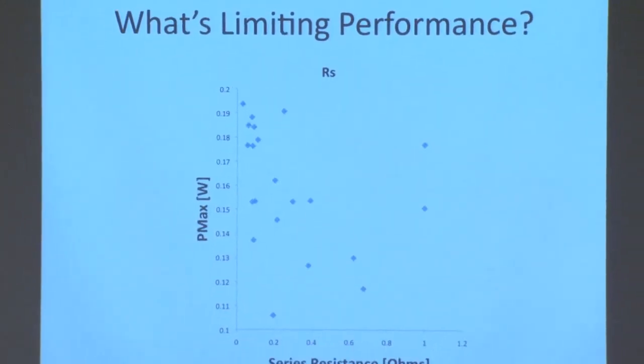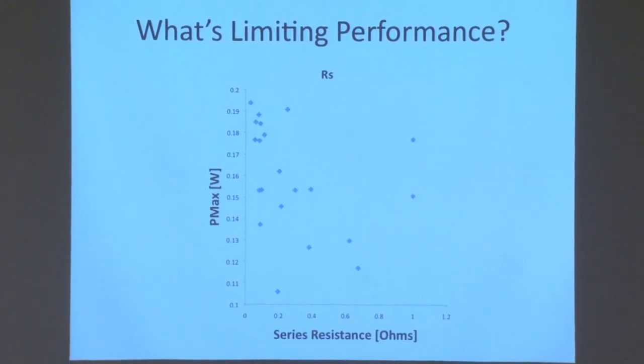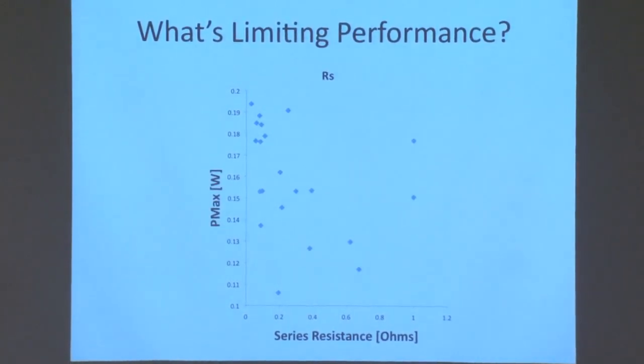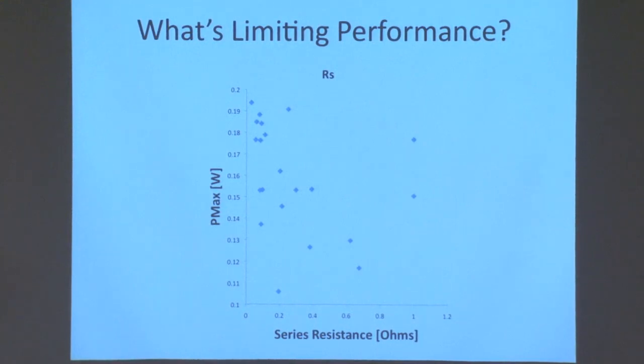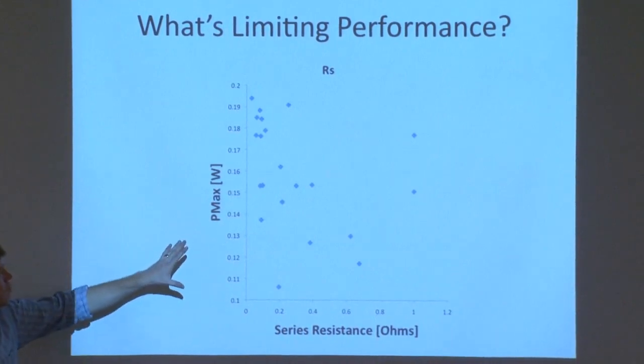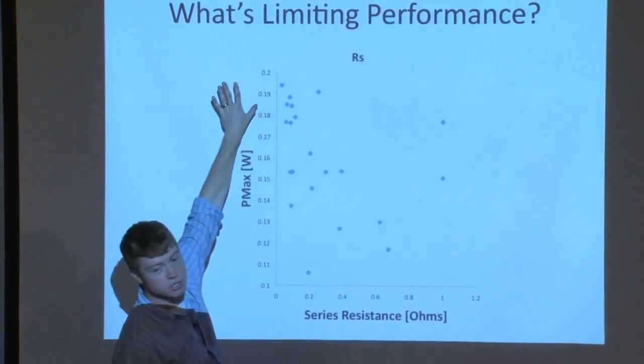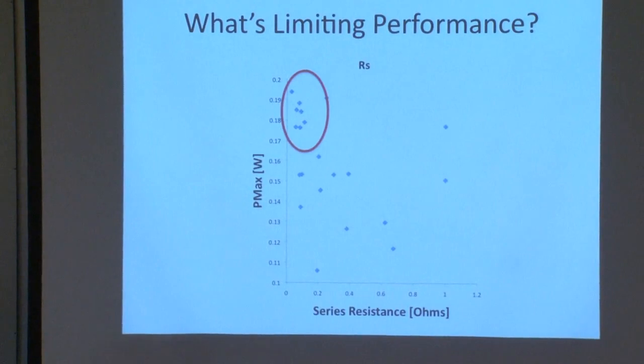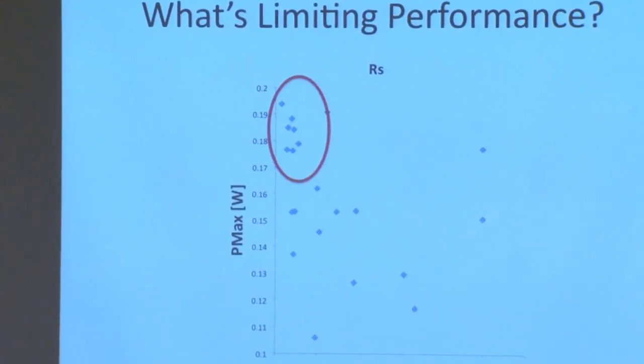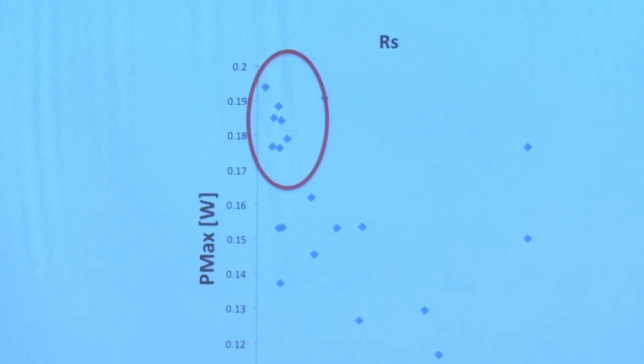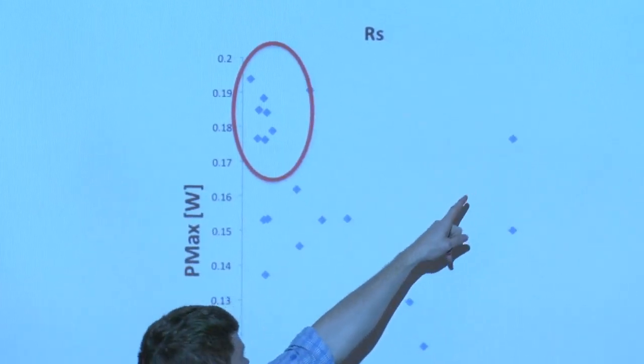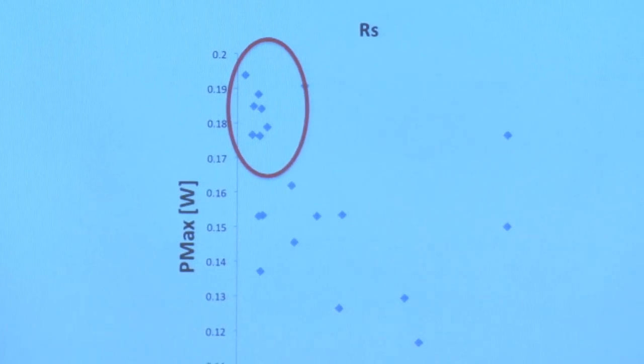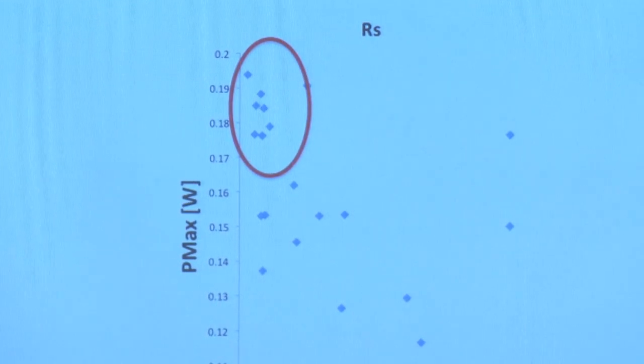Additionally, I plotted the series resistance that I calculated from your dark IV curves against your maximum power. I also removed all the cells that were broken. I'm sure if I actually normalized them, some of the cells that were broken actually performed a lot better. And I'll get into maybe why that was the case in a second. But really the take-home message is that our best performing cells are all clumped over here. And so you can see that our best cells have a very low series resistance. That's not always the case. There's some outliers like this guy here, and I don't know how that happened. But some really interesting things going on. I'm still trying to sift through it.